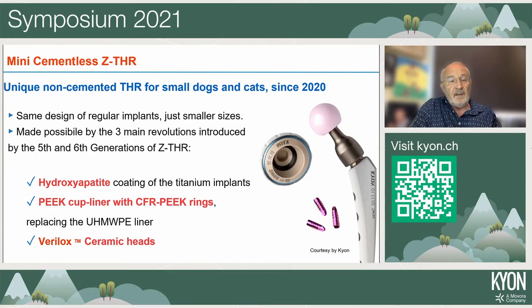Then, very important, the PEEK cup-liner with the CFR-PEEK rings that substituted the ultra-high molecular weight polyethylene liner that was causing some erosion in few years. So that was not providing a full life guarantee as we want to have for our total hip replacement in dogs. And then the ceramic heads that reduce even more the wear.